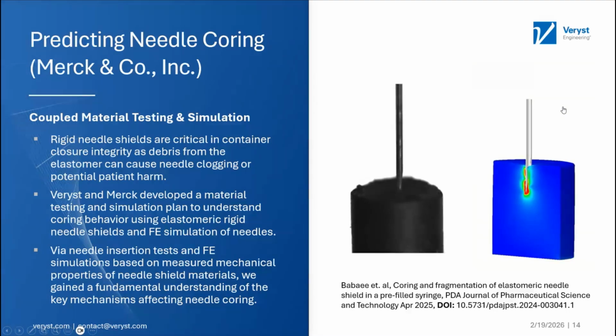The problem in general is that in pre-filled syringes, there's a device called the rigid needle shield, which has both a thermoplastic part as well as a soft elastomer part that the needle then punctures a little bit during storage and transport to protect both the drug product and the needle. You can see the needle and that elastomer there over on the left. But what can happen sometimes is that the needle can experience coring, where the elastomer actually blocks the needle and blocks the drug product from coming out, which is obviously a problem if you're trying to deliver this. Or you can potentially deliver an elastomer particle into somebody, which is also something that we need to avoid.